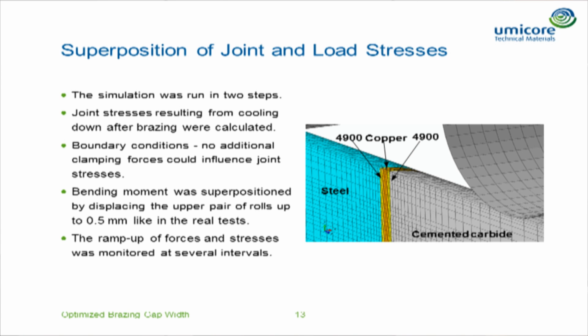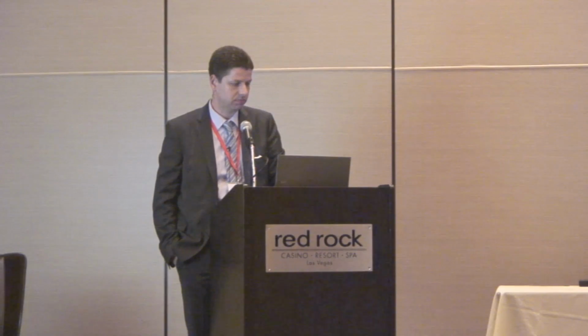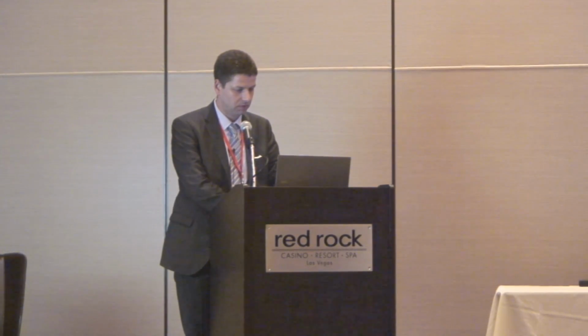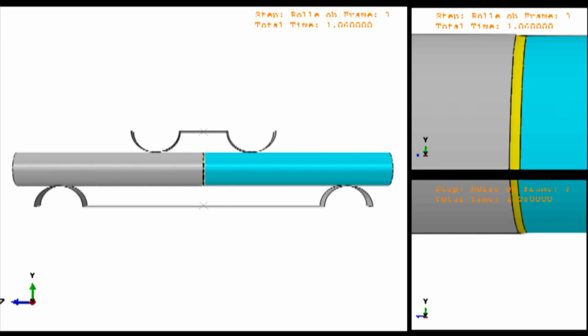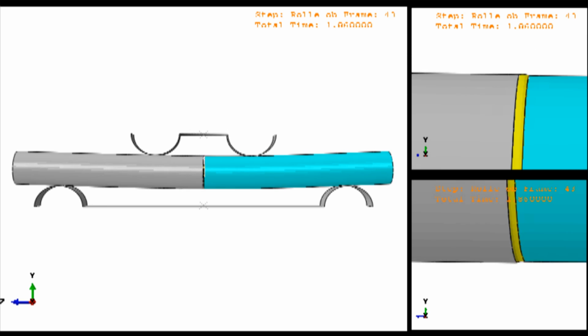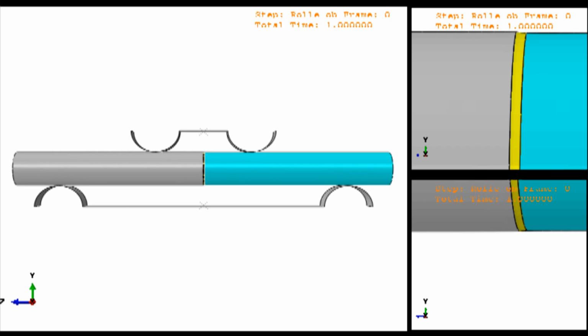What we did was a two-step calculation. First, we made the calculations after brazing and had a look at what the stresses are in the parts at that stage. And then afterwards, we applied different loads to the part and had a look at what happens to the part. Also here a short video, but I will only show you the one. There you can see how the simulation works, and it's quite interesting. On the top side, the copper in this simulation, or the brazing alloy, was pressed out, and on the bottom side it was sucked in.